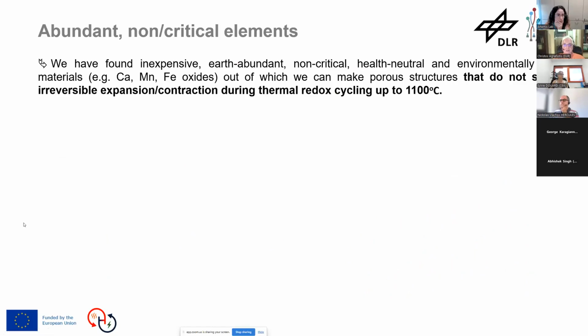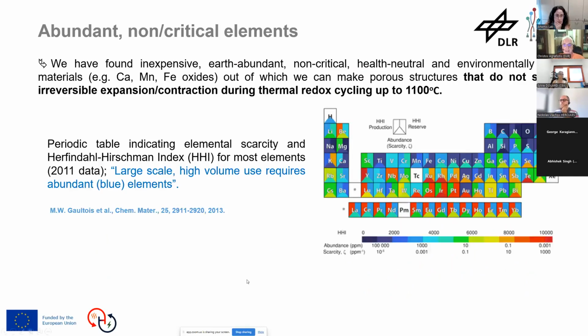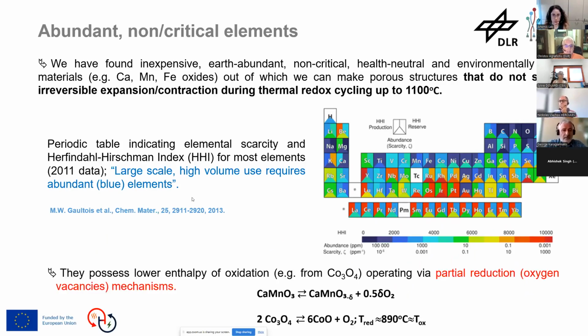So we have found non-critical earth-abundant elements based on calcium, manganese, and iron oxides. They are the blue elements in this so-called Herfindahl-Hirschman index, which demonstrates visually that any large-scale, high-volume energy application requires these abundant blue elements. Our materials, calcium, manganese, iron oxides, are definitely within the blue spectrum. The disadvantage is that they possess a lower enthalpy of oxidation, since they operate as a partial reduction mechanism rather than a phase change as the cobalt oxide.